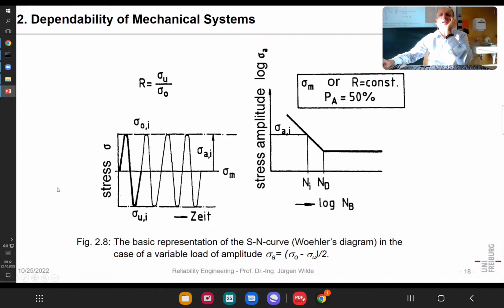So, okay, and then Mr. Wöhler found out, when you do your experiment, what is the stress level, the stress amplitude, you start with? You cannot be larger than what? You cannot be larger than the ultimate tensile strength. Yeah, that's clear. And when you go to ultimate tensile strength, or better, yield strength, how many cycles will you have? You destroy it, so you have half a cycle. Yeah, that's not really fatigue, but here your curve will start. Half a cycle, yield strength.